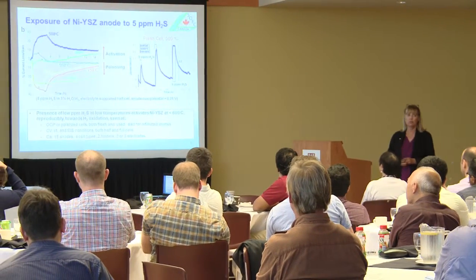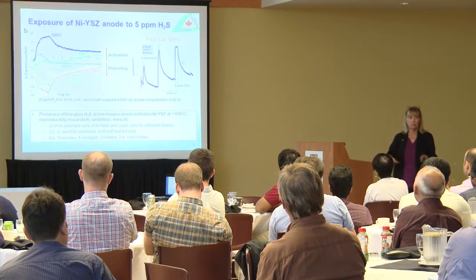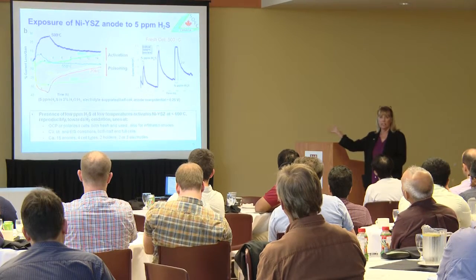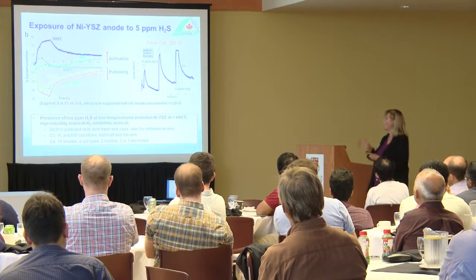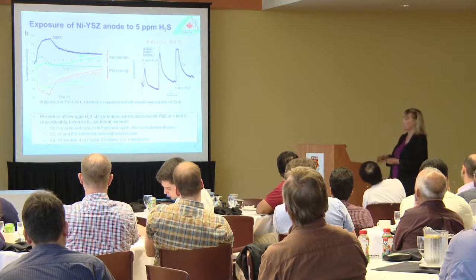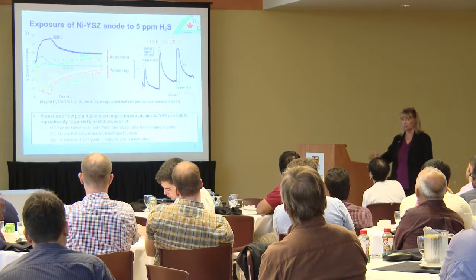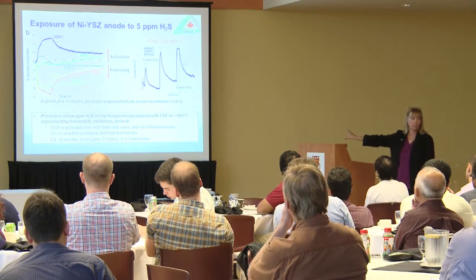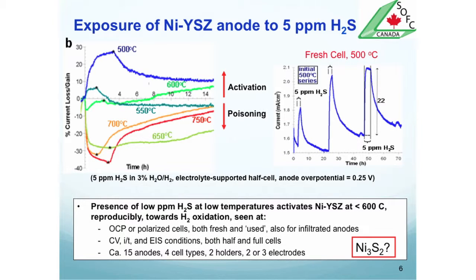This on the right is for a fresh anode, never seen H2S at higher temperatures. And you can see at 500 degrees, when you bring H2S in, the current goes up. When you take it out, it goes down. And in the bullets there, hopefully you can see them, we have put this through every possible pace of types of cells: 2-electrode, 3-electrode, open circuit, polarized, positively polarized, negatively, different cell holders, and so forth, and this result has persisted.